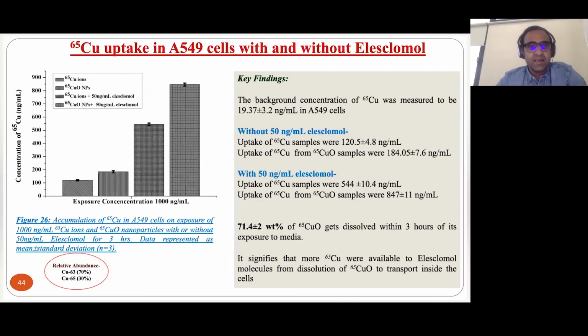And what we found out was, in the case of A549 cells, if we are just exposing our cells with copper 65 ions, it is also going through the cell, because remember, there is always this ionic channel pathway through which this copper can go inside the cell. And that is causing a concentration of somewhere around 100 nanograms per ml inside the cell. When you take copper 65 oxide nanoparticles, remember that they have two ways to enter inside the cell. One is through dissolution, which is the ions, and second is the particles themselves can also get internalized through the endocytotic pathways.